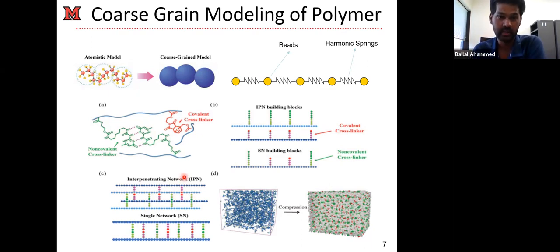That's very interesting. So after making those polymer chains, we randomized this whole thing in our simulations so that there is proper mixing of those polymer networks. When we ensure that our mixture is homogeneous and isotropic, we compress our system to the desired density. In our case, it was a very low density, like the density of water, a very soft, rubbery material. When we got this desired density, then we performed our testing, like the tension test or thermal conductivity measurements, on these specimens.